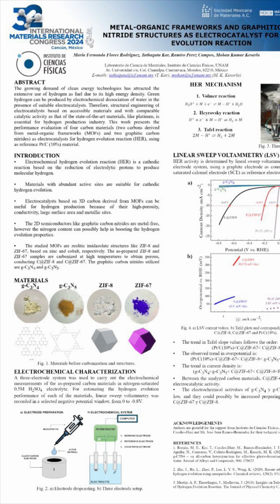The studied MOFs are zeolitic imidazolate frameworks like ZIF-8 and ZIF-67, based on zinc and cobalt respectively. The as-prepared ZIF-8 and ZIF-67 samples are carbonized at high temperatures to obtain porous conducting carbons. The graphitic carbon nitrides utilized are g-C3N4 and g-C3N5.